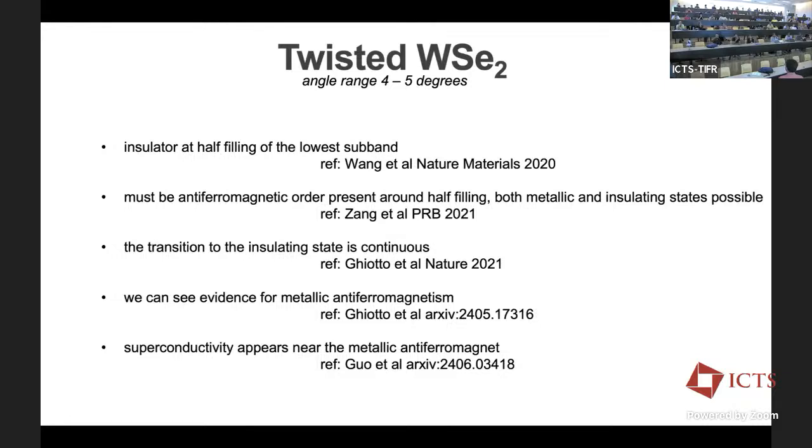Yeah, so certainly it's not a ferromagnet. So we see no hysteresis. And there have been some optical measurements which would have seen ferromagnetism if there was ferromagnetism. At lower twist angles, you do see ferromagnetism appear. So ferromagnet phases are not far away from this. And Xiaodong has some data on ferromagnetism at lower twist angles. But at these twist angles, there's no evidence of ferromagnetism from optics. And there's no hysteresis seen in transport.